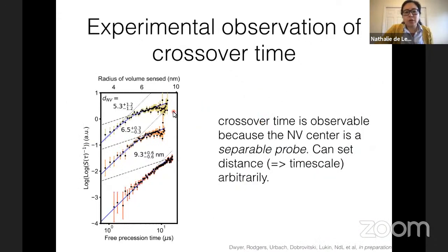Okay, so now armed with this understanding of the data, we can go back and measure the NV centers in a way where we really oversample this coherence decay, so that we can look for this critical crossover time. And indeed, we do see this dramatic change in slope. Remarkably, this crossover time really does just look like the distance from the surface, which we can measure independently using proton NMR.